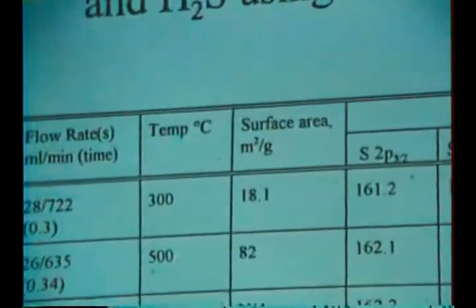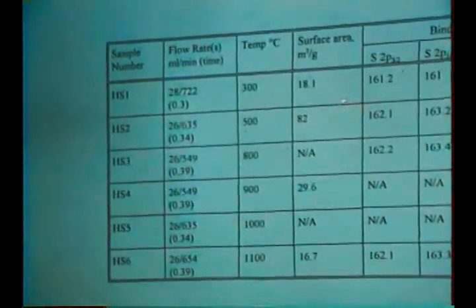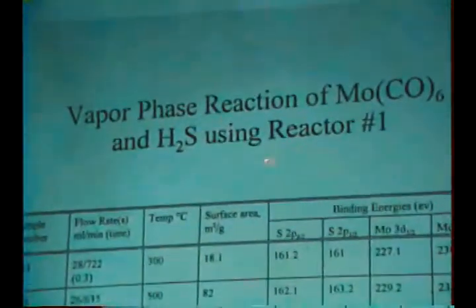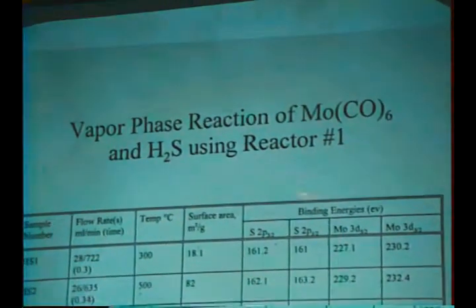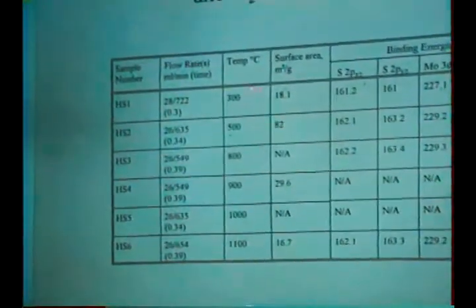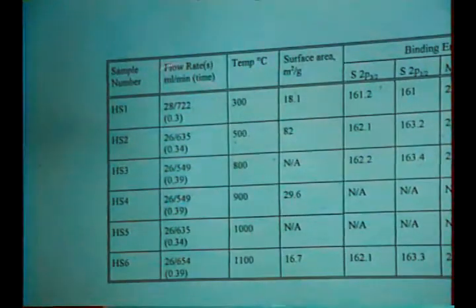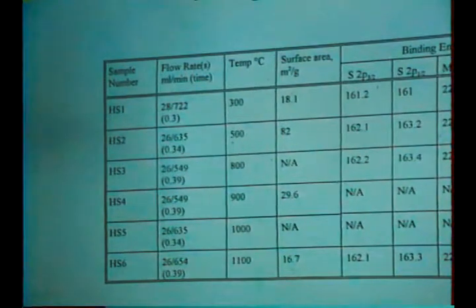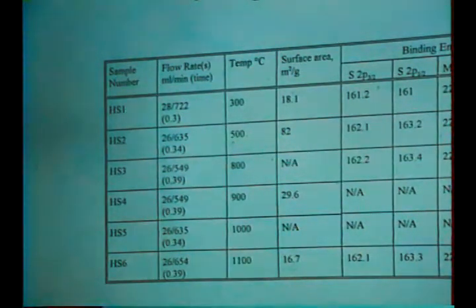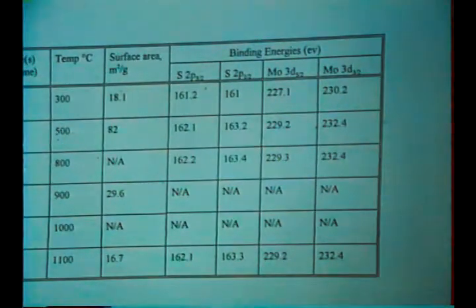Now let's look at some data from these reactions. This is some data that I collected using reactor number 1. That's with the water jacket at the top, the one that you saw in the previous slide. What you'll notice here is the furnace temperature and the gas flow rates. As the temperature increases, I analyzed the surface area of the corresponding materials. And what you'll notice here is that there is a maximum at 82 meters squared per gram. Now, this to me was a little bit surprising at first because I expected there to be a trend all the way through here. We submitted the materials to Union Carbide, and Golub Salita was able to do the XPS work for these materials.